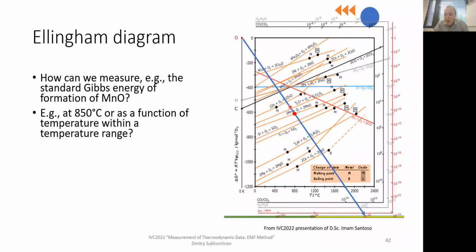Well, it's rather straightforward. We need metallic manganese, we need MnO, we mix them, then we need an oxygen ion conductor, solid electrolyte; probably stabilized zirconia would do the job. I believe the challenge is to have extremely pure argon gas for protective atmosphere, or we need to do some other trick. Otherwise, it will ruin the equilibrium oxygen pressure generated there, because it is so low. Maybe we need to somehow seal that compartment so that there is no dynamic atmosphere there at all. And then the reference side can be probably many things. Oxygen can do the job, I believe.